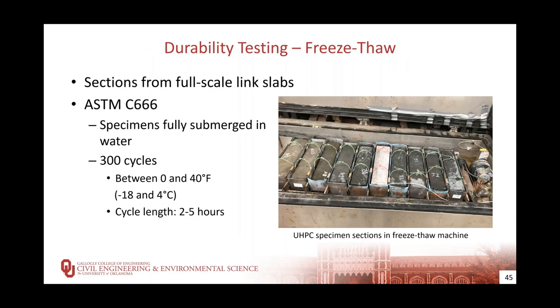Now for freeze-thaw testing, two smaller sections of each specimen will be cut. In accordance with ASTM C666, these sections will be submerged in water in a freeze-thaw machine, as seen in this picture. They will be taken through 300 temperature cycles at a rate of 2 to 5 hours per cycle, with each cycle going from 40 degrees Fahrenheit down to 0 degrees, then back up to 40 degrees.